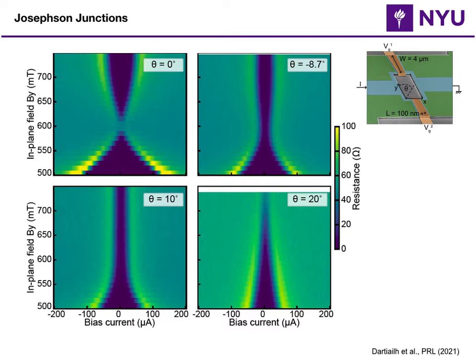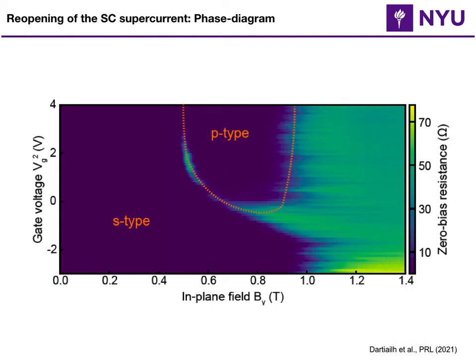So if we do a phase diagram for the event that I just described as a function of gate voltage and in-plane field, you see that there are gate voltages where you can go as much as you want in the in-plane field, but you do not see a gap closing. And above some gate voltage, where presumably spin orbit is strong, you can actually see a transition from what we call S-type and P-type superconductivity.